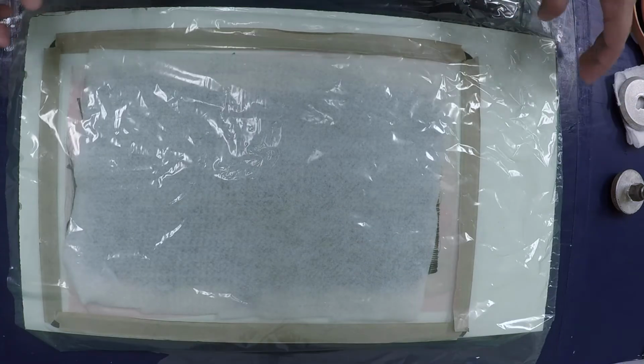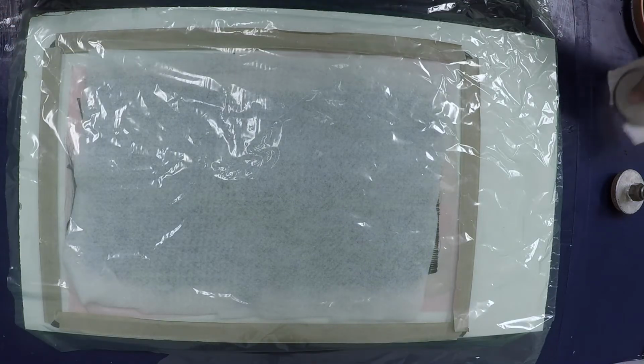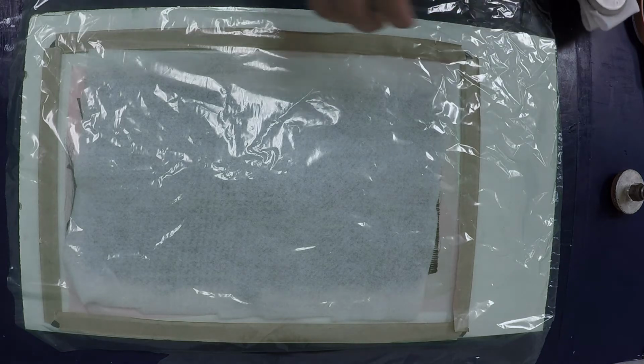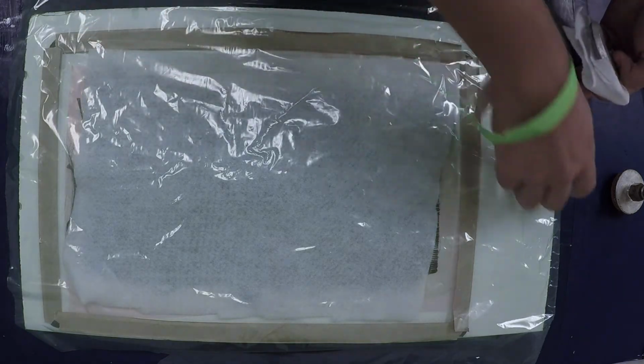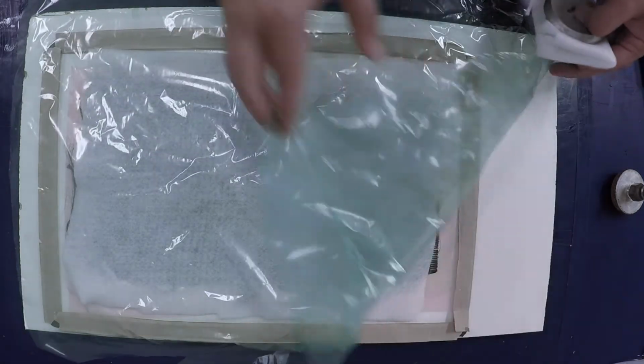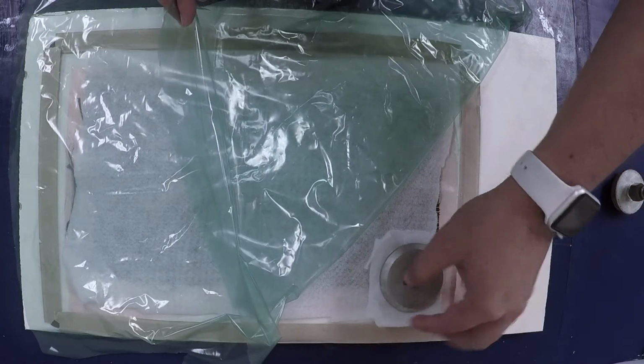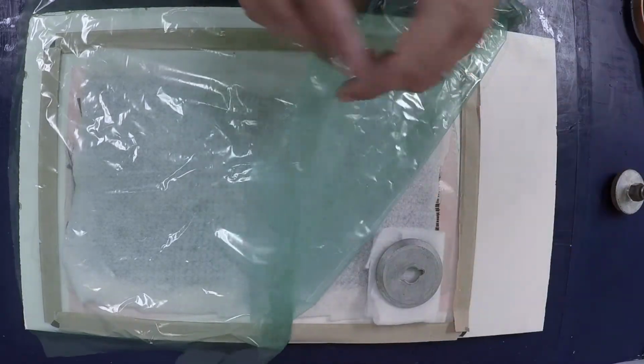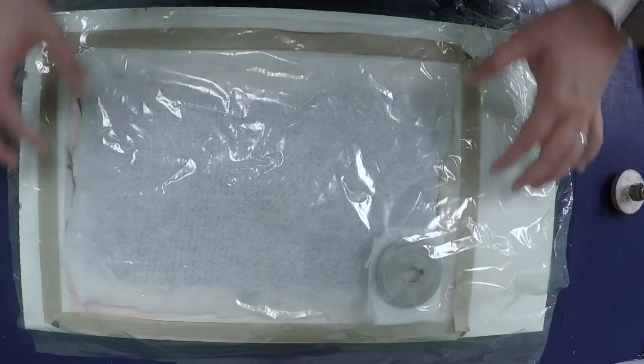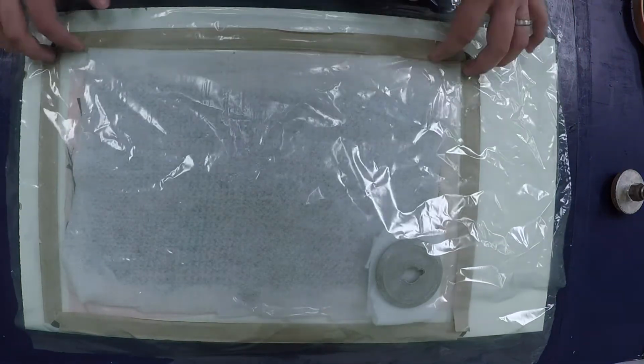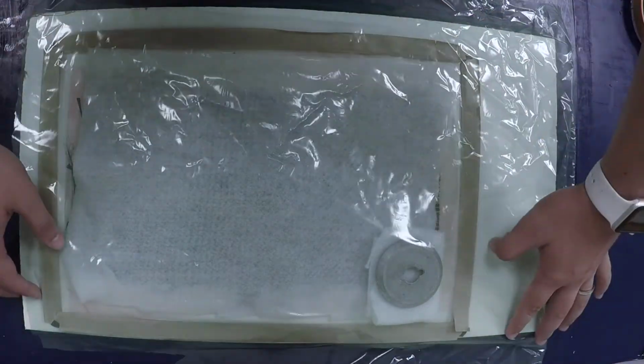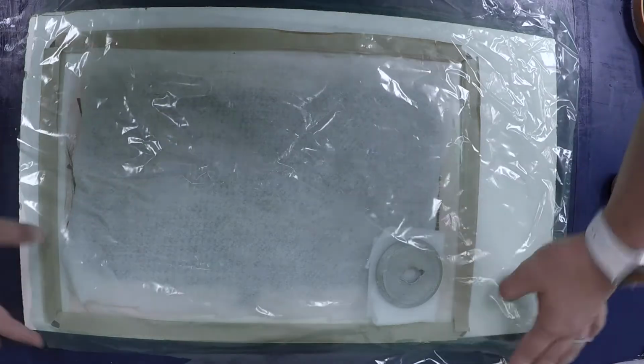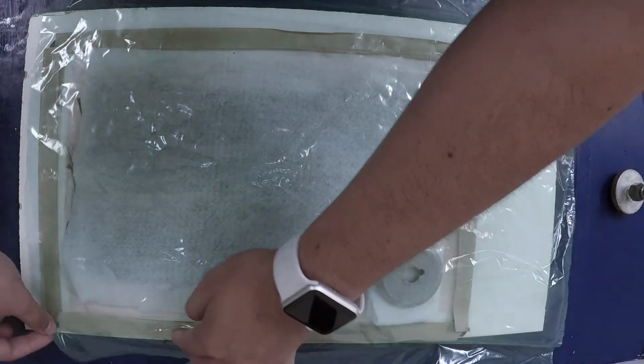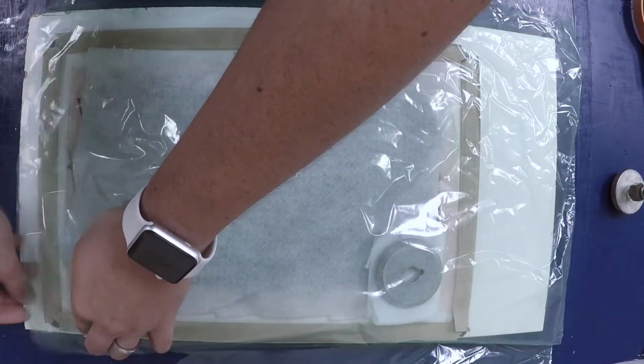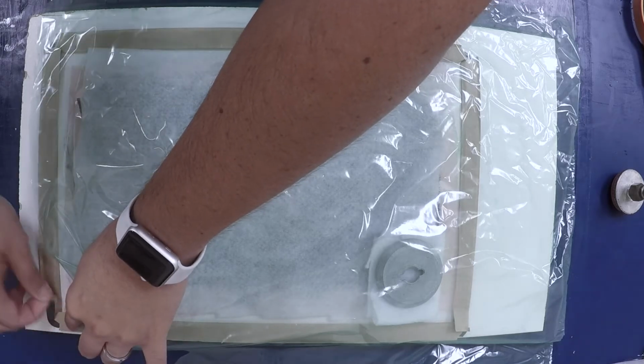However, before we place down the vacuum bag, we must first place down the vacuum port. When placing down the vacuum port, be sure to place an extra couple of layers of bleeder underneath to give it more cushion and prevent it from sealing itself to the mold. This is also to protect the valve from being contaminated with epoxy if there is an excess of epoxy in the area where it is placed down. Do not place the vacuum port over the final product.